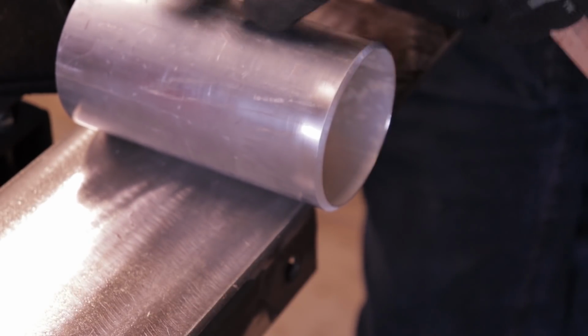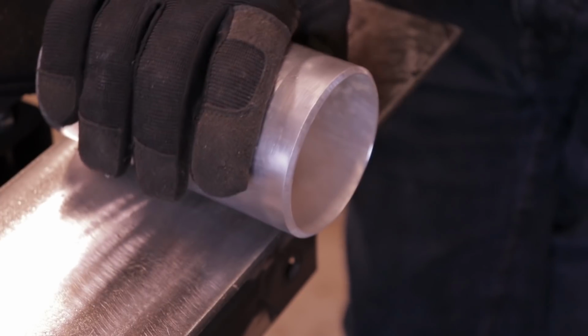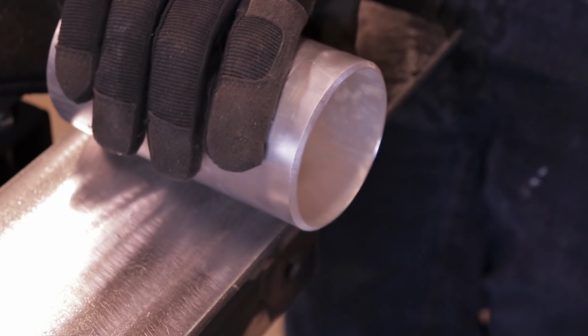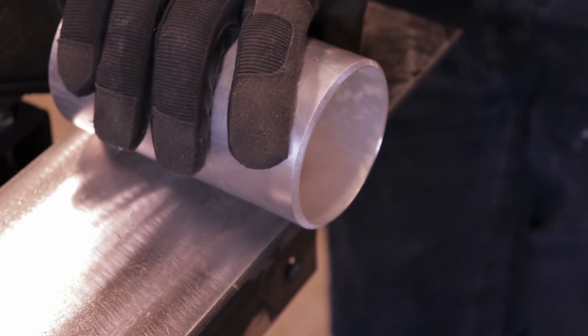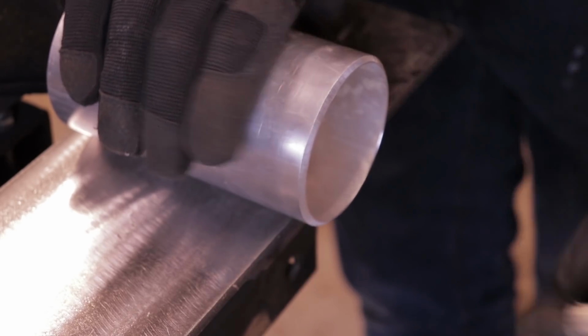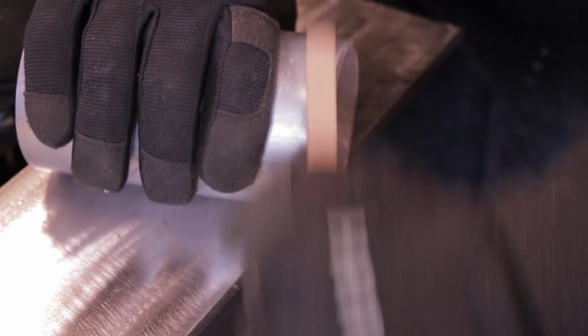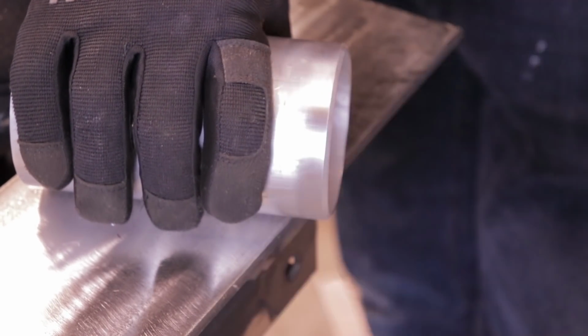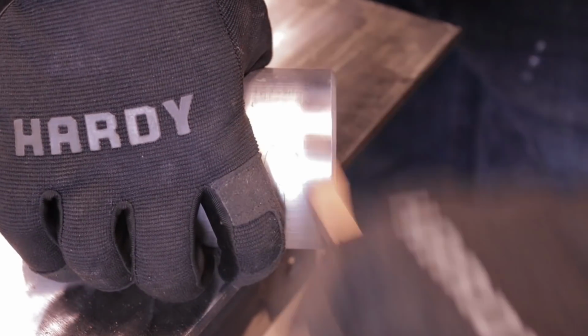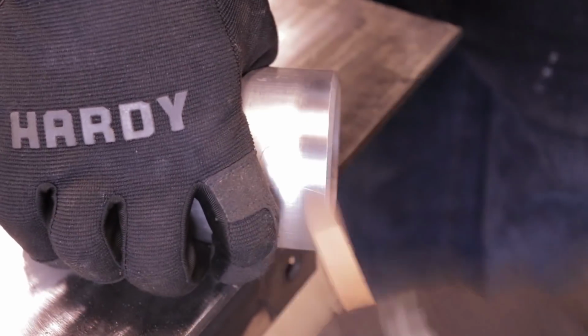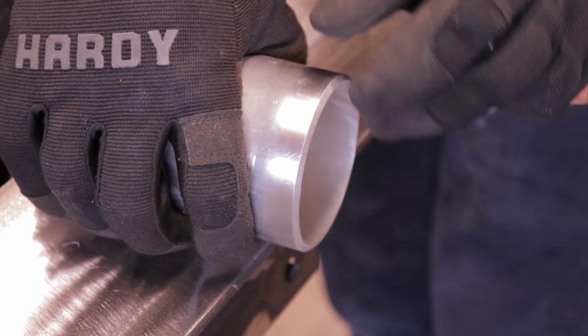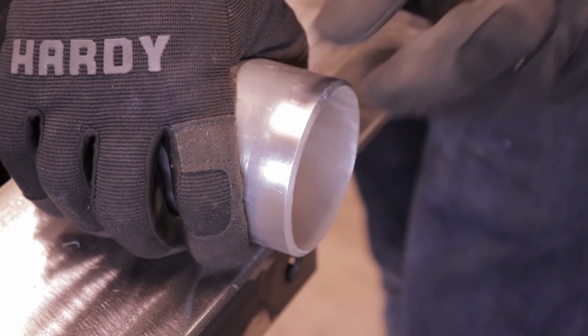So especially if it's old. If it's brand new, just out of the paper, we usually don't unless it's something really important, like if it's a water pipe, if it's a fuel tank, something like that, then I'll wire brush it. But if it's brand new metal off the router table, it's good enough, it's good to go. You don't have problems welding. When you're welding older material that you haven't cleaned, your puddle doesn't flow quite as nice as it does on something that you've wire brushed and cleaned. And so you get all these jagged lines. Your puddle almost doesn't melt as smooth all the way around.